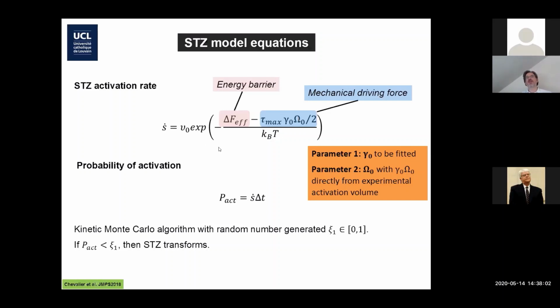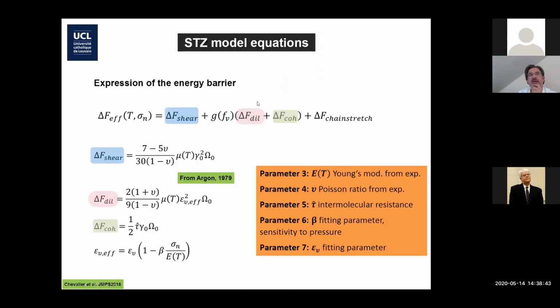And so there is a certain activation rate, which of course will depend on temperature. The higher the temperature, the higher the probability that you can do the jump over the barrier, and this probability also increases if your mechanical driving force increases, meaning if the stress is larger. The probability of activation is the activation rate multiplied by the time increment over which you're looking. And we use a kinetic Monte Carlo algorithm where you generate a random number between 0 and 1, and if the probability is higher than your random number, the STZ is activated. The question is, what is the form of the energy barrier? For the energy barrier, we just borrow what Argon has proposed, and that's what Schuh is also doing.